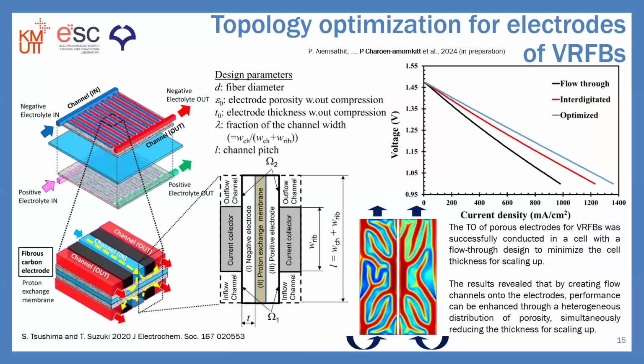And for this study, from one of my master students, we would like to address 2 issues found in the vanadium redox flow battery. Firstly, the cell architecture, which features the flow channel on top of the electrode, has been widely adopted due to its superiority. However, during the scaling up, this design may lead to unnecessary thickness in the stack, hindering the ability to achieve higher performance, higher voltage, and resulting in increased loss. And secondly, in previous studies using topology optimization to seek the optimized design, the system was often simplified by focusing solely on the bottleneck electrode. And therefore, it remains unclear what the optimized design would be when considering full cell models.